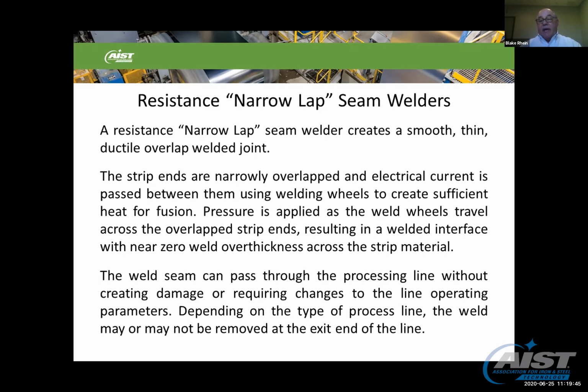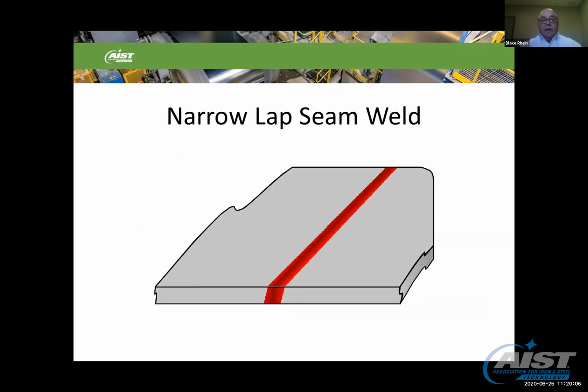The weld seam can pass through the processing line, generally without creating damage or requiring changes to the line operating parameters. Depending on the type of process line, the weld may or may not be removed at the exit end of the processing line. A narrow lap seam weld graphically looks something like that. It's near parent metal thickness after the weld is made and is sufficiently strong to hold through the process line.